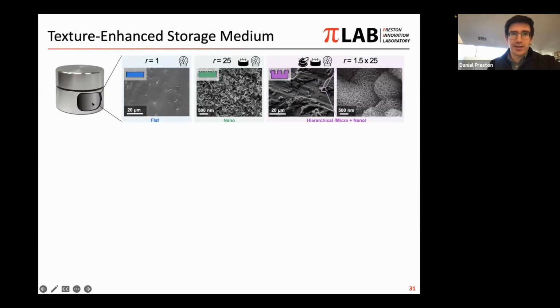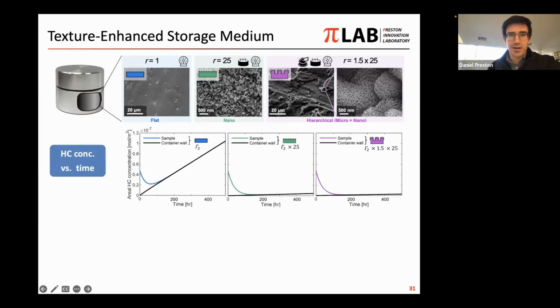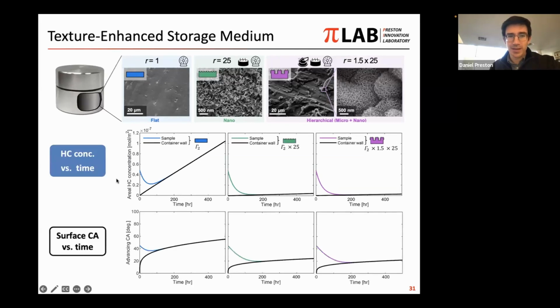And so again, looking at the container, if we look inside of the inner wall, we had different levels of roughness or surface area. The model predicted the hydrocarbon concentration versus time for the sample, as well as the container wall. The container wall was initially clean. The sample was initially slightly contaminated in the model. And we could also look at things like the contact angle versus time. And these increase, but we find that the higher roughness of the wall results in a much lower level of contact angle and a much lower increase over time of the contact angle, even hundreds of hours later, compared to just the flat storage container.